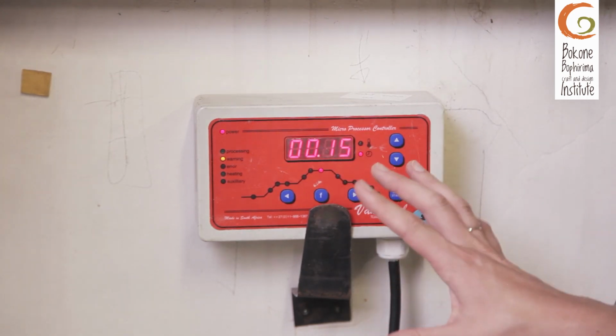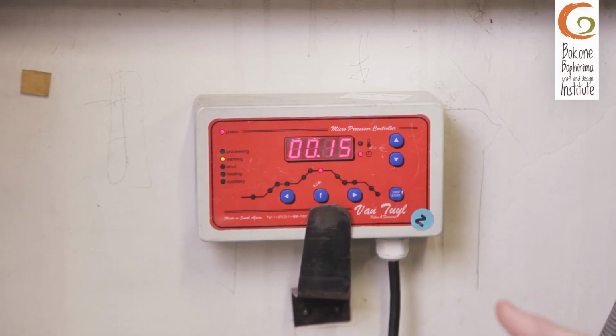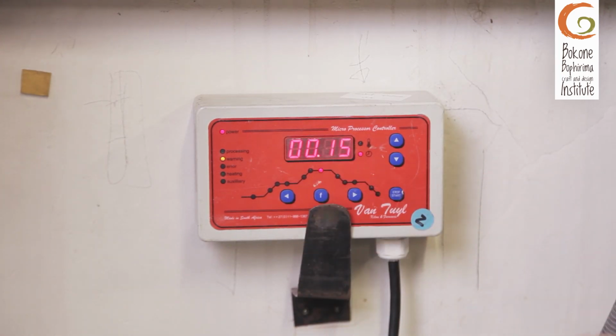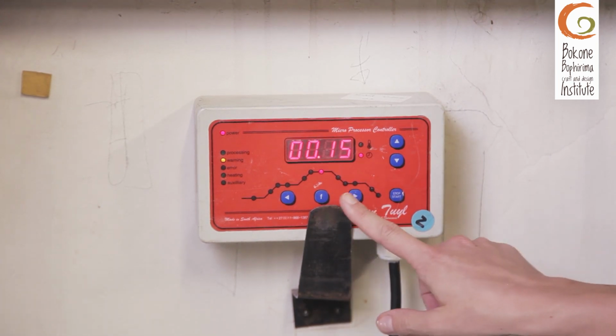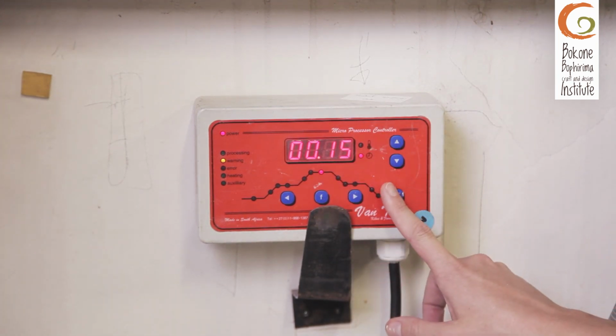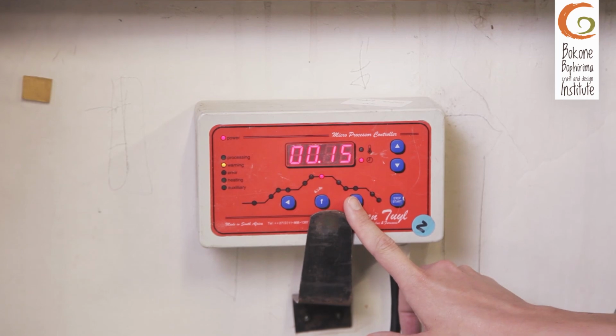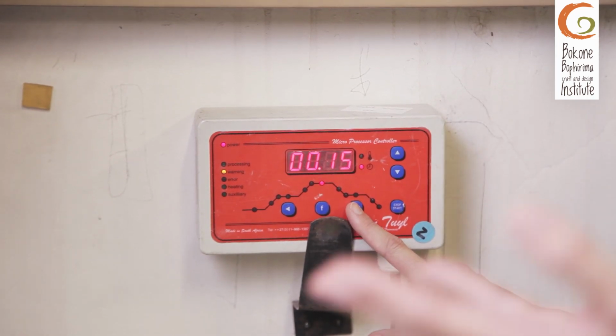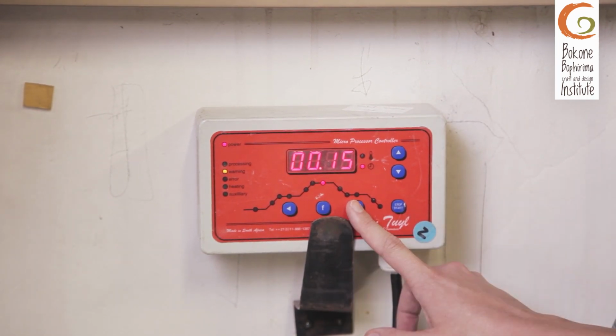I'm going to hold it there for 15 minutes to ensure that all my edges are soft and melted and that there are no air bubbles captured in between the glass. I then need to crash cool the process to be able to capture that point and make sure we capture that glass in that moment.